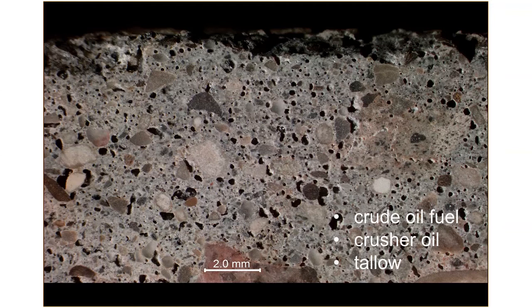So crude oil as fuel for the kilns to burn the limestone and produce clinker, crusher oil or tallow, again used as a grinding aid in crushing this material, and likely put a surfactant of some kind of organic material into this concrete and produced air just by sheer accident.